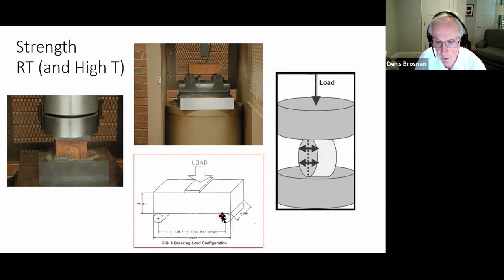Now, some labs use 4-point bending, 2 bottom supports and 2 upper supports applying the load. Some use 3. It's also possible to estimate the tensile strength of the ceramic by compressing a cylinder on its side, and that's the same as pulling it apart from a stress standpoint. So we get a maximum stress at failure called a diametral compressive strength, which is actually like a tensile strength. You can measure tensile strengths of ceramics. It's harder to do because typically you have to form a specimen that you can grip in a machine's vise grips. Now you can measure these at room temperature and high temperature and compare the results, and that gives you some more information, which I don't have time to talk about.